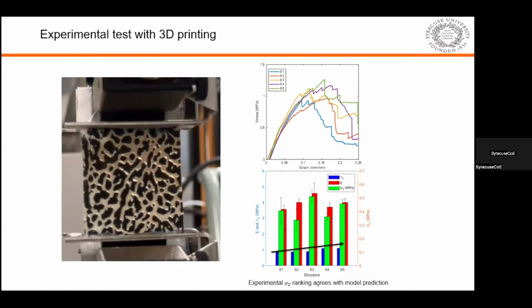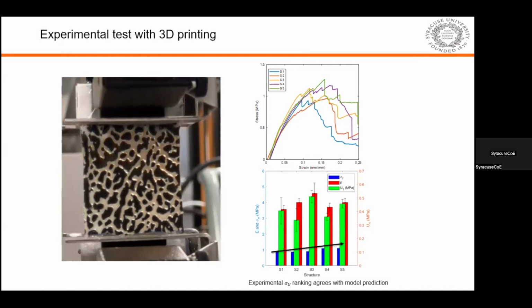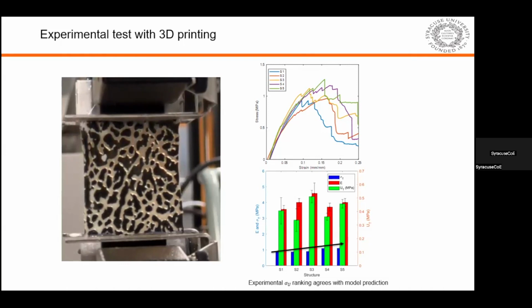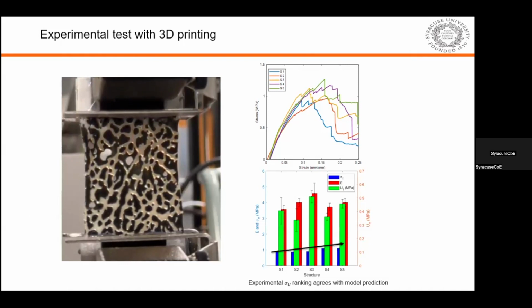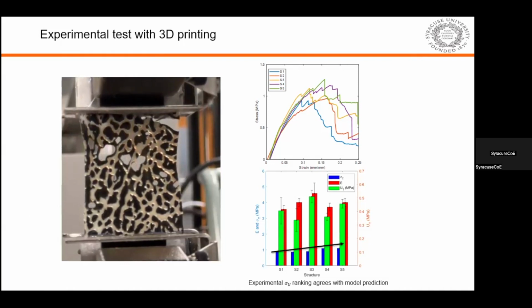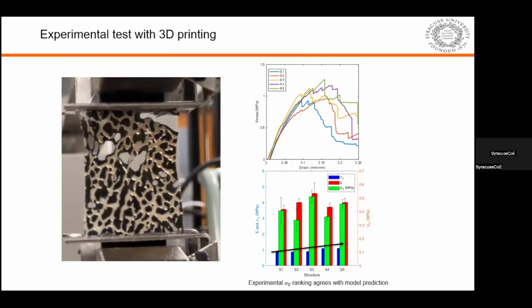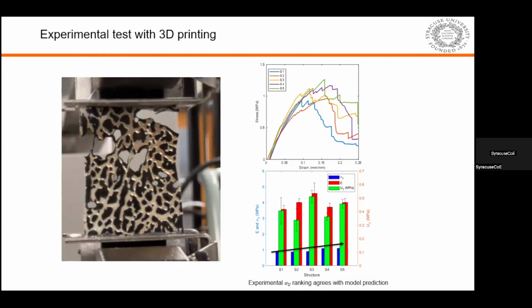So we use aluminum tabs to glue the specimen, and then use this machine to apply loading. And we get the stress strain curve, and we compare the ultimate strengths of the 5 samples. So this rank perfectly agrees with the prediction from the generative AI together with our mechanics analysis. So we are happy about that. We're going to repeat this test on more structures to verify that this method is useful and efficient to generate arbitrary designs of composite.